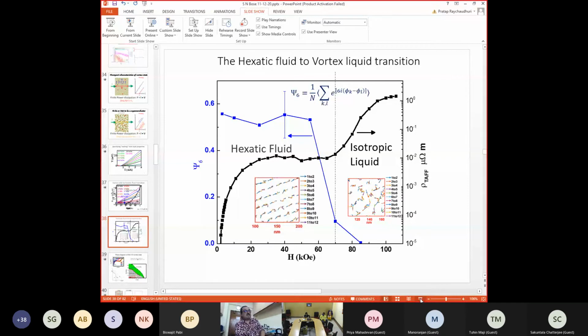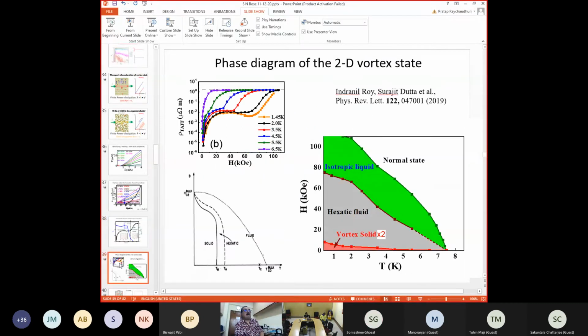So now using these transport signatures, I can do this measurement at many temperatures, and then I can construct the phase diagram. And what I see is that I have this vortex solid here. At some field, it goes into a hexatic fluid, and at a higher field, it goes into an isotropic liquid. So, since I'm short of time, I'll end here.